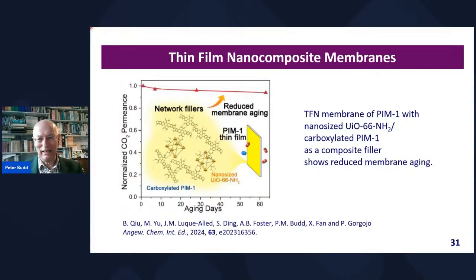again involving people in chemical engineering at Manchester and at the University of Zaragoza, focused on thin film nanocomposite membranes. And in this case, again, we're playing around with what we can do with a filler. It was a MOF, but in this case, the MOF formed a composite with a carboxylated version of PIM-1. And so there are lots of things we can do by combining polymers and other things in the right way to obtain membranes with interesting properties. And one of the things we're looking at is reduced membrane aging.